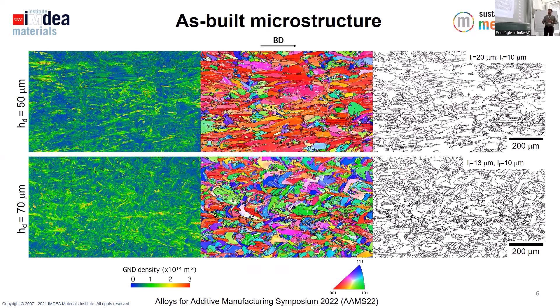Here is where we see the differences between the 50 and 70 micron samples. In the 50 micron sample we have a clear columnar microstructure, which is typical from LPBF samples, with a strong 001 texture parallel to the building direction. Whereas with the 70 micron sample, we have a much weaker texture. Looking at grain size, these are the line intercept values for both the transversal and longitudinal directions. The grain size in the transversal direction doesn't change much, but the aspect ratio does — another indication of columnar grains in the 50 micron sample.